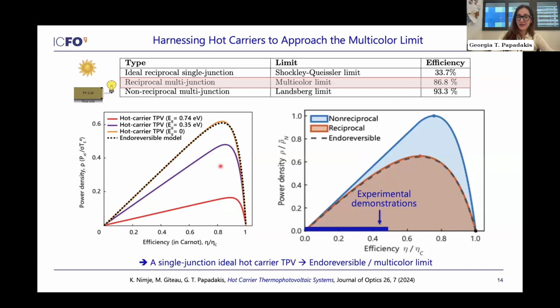Now, if I look at the diagram that I showed before, here are 3 different curves that show the power density and efficiency of a hot carrier TPV as I decrease the bandgap of the cell. By decreasing the bandgap, I allow more and more photons to come into my cell, and I integrate over a larger spectral range, so I get more power density. As you can see, for 0 bandgap, I recover this endo-reversible limit, which is the multicolor limit described in the previous paper that I showed you. So with a single junction ideal hot carrier TPV, I could reach the endo-reversible limit. Of course, this is theoretical work, and hot carrier PVs are being intensely investigated recently.